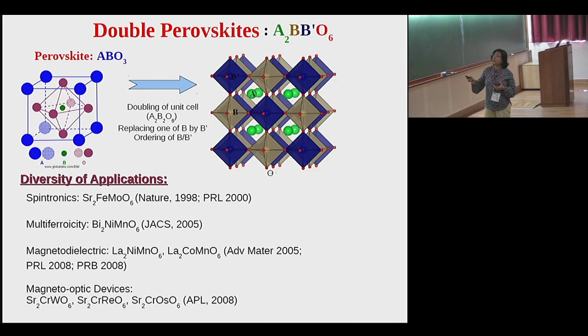Now you take this perovskite structure and make it double. Therefore, the formula becomes A2B2O6, and since you have B2 instead of a single B, you can afford to put 2 different transition metals, namely B and B prime, therefore making the formula A2BB'O6, and the BO6 octahedra and B'O6 octahedra have a rock salt ordering, alternate ordering along all three directions. This class of compound is quite promising because there is a diversity of application.